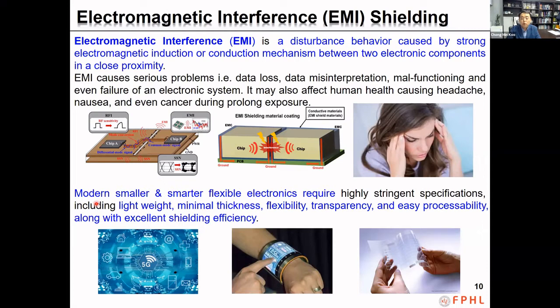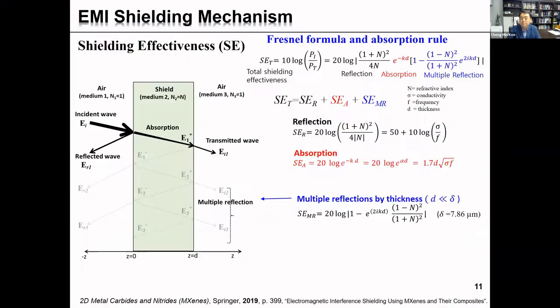The modern, smaller, and smarter flexible electronics require very stringent specifications such as lightweight, minimal thickness, flexibility, transparency, and easy processability, along with excellent shielding effectiveness. The shielding efficiency is quantified by shielding effectiveness, which is defined as the logarithmic ratio of the power of the incident and transmitted wave. The total shielding effectiveness can be achieved by shielding by reflection, shielding by absorption, and shielding by multiple reflection effect.